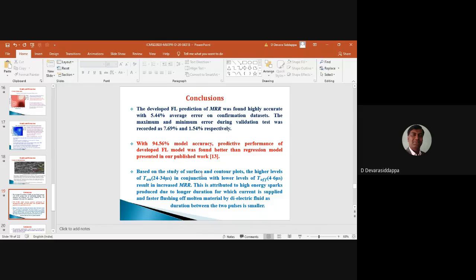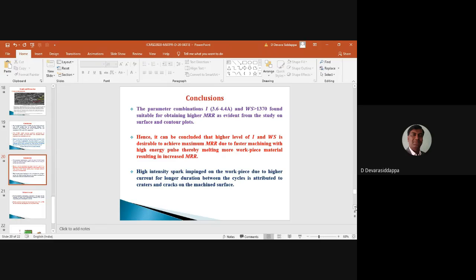Based on the surface plot and the contour plot, higher levels of pulse on time in conjunction with lower values of pulse off time result in higher MRR. This can be attributed to the high energy spark produced due to the longer duration for which the current is supplied, and faster flushing of molten material by dielectric fluid as the duration between the two pulses is smaller. Continuing with the conclusions, for current and wire speed, higher values are desirable to get higher values of MRR, as evident from both the surface plot and contour plot. Hence, it can be concluded that higher levels of current and wire speed are desirable to achieve maximum MRR, due to faster machining with high energy pulses, which melt the workpiece material, in turn giving a higher material removal rate.